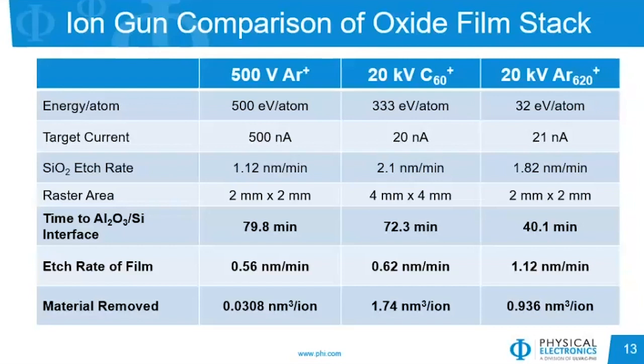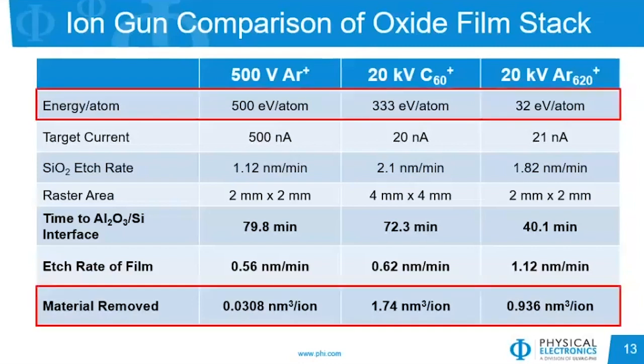Similarly, we have a 20 kV C60 beam that we will be analyzing this with, and also a 20 kV gas argon 620 cluster. And so we go from 500 eV per atom down to approximately 32 eV per atom. There are some other parameters in here related to the conditions used for this study. And I would also just like to point out, as I mentioned before, the general efficiency of the monoatomic being less than that of the cluster sources, where we can see for each incoming ion, the material volume that is actually removed is least with the monoatomic argon and higher with the cluster sources.